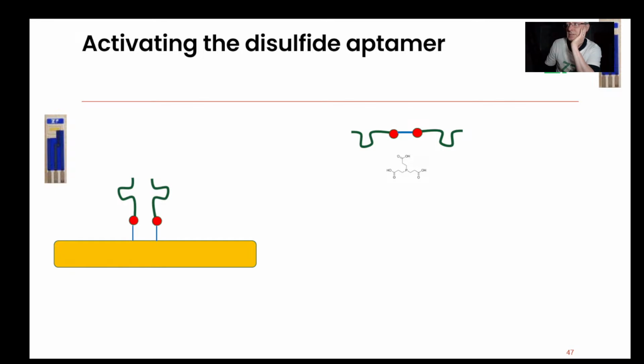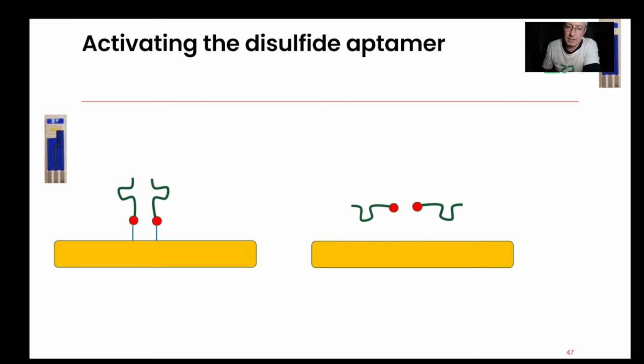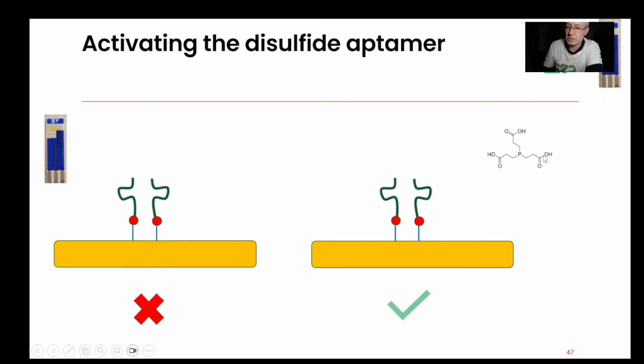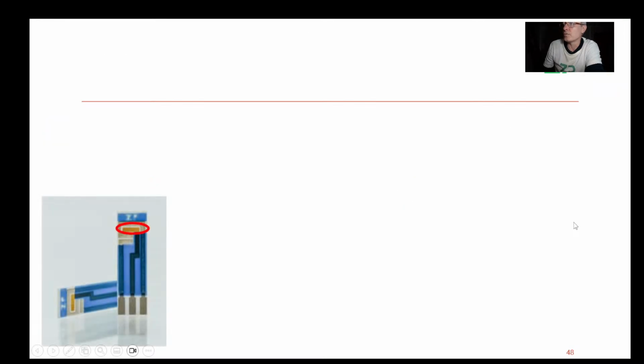You should make that more deterministic by actually just putting in this reagent, letting the reagent reduce the disulfide bond, and then you should get a more repeatable surface. We actually use quite a large excess of this reducing agent, something like 50x, even sometimes 100x of this. It's hard to call on this because each aptamer, the ability to reduce that sulfide bond can be a little bit sensitive to the actual aptamer itself, but we use quite an excess of material to get that reduction. So we don't rely on the gold. I think we've tried doing that, it doesn't work for us, and we definitely do a reduction of the bond.